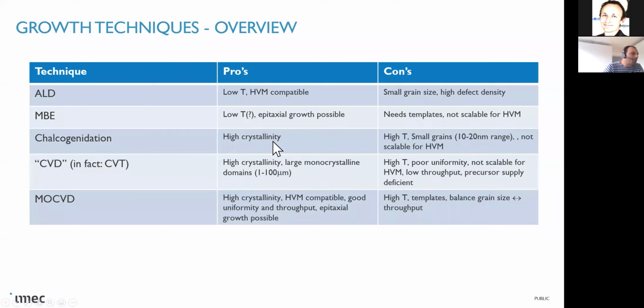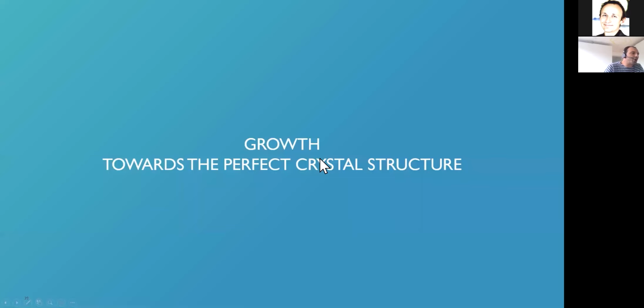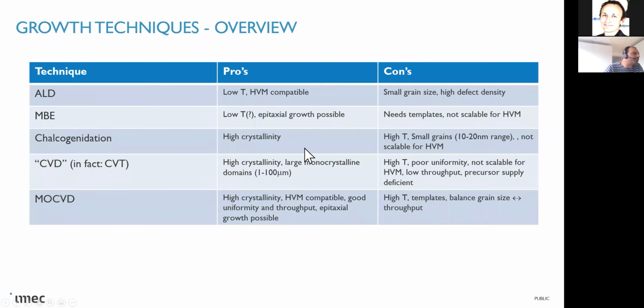So, now I will go to growth and discuss how we think we need to make steps forward towards the perfect crystal structure, because that's basically what we are after at the end of the day. There are different techniques that you can use to do that. ALD has the advantage of being normally low temperature, and it's very established in the industry. But what we found out is that in the last 7-8 years, a lot of people tried to grow 2D materials with ALD, but typically they did not succeed in achieving high quality materials. With MBE, you also have a relatively large window, but this is typically not something that is really scalable to high volume manufacturing, and also typically the good results need the right templates.